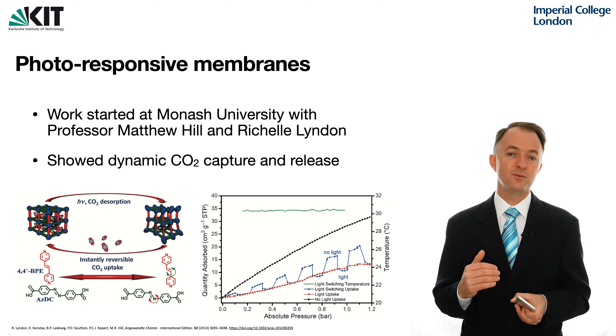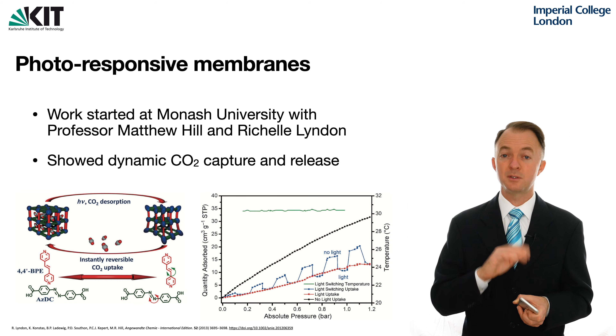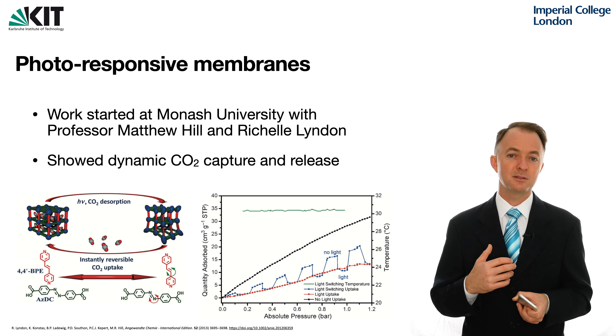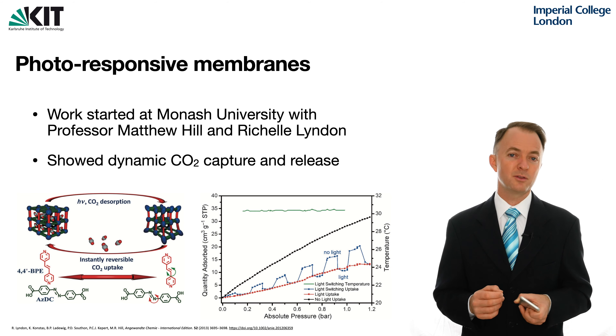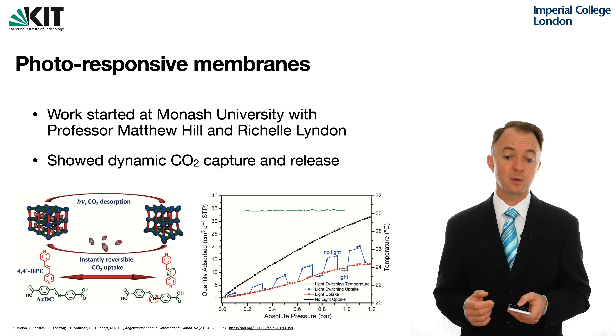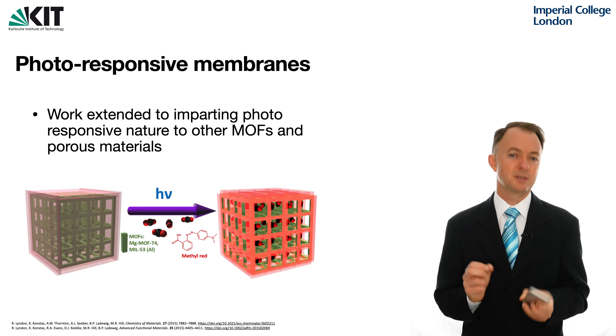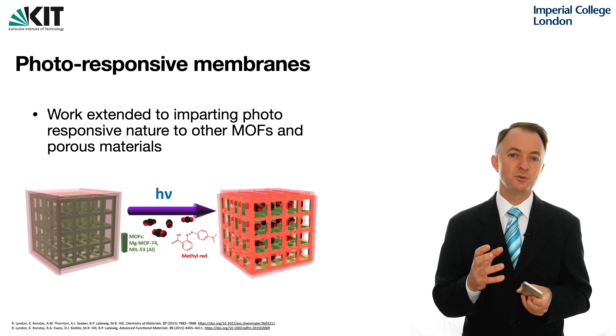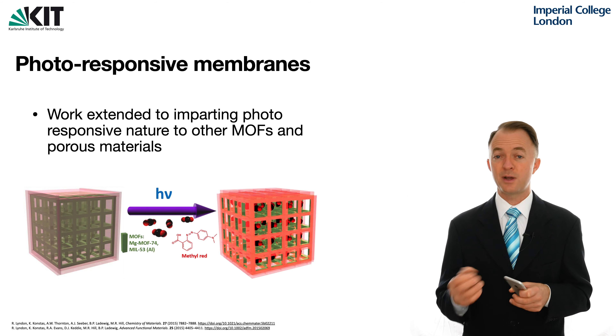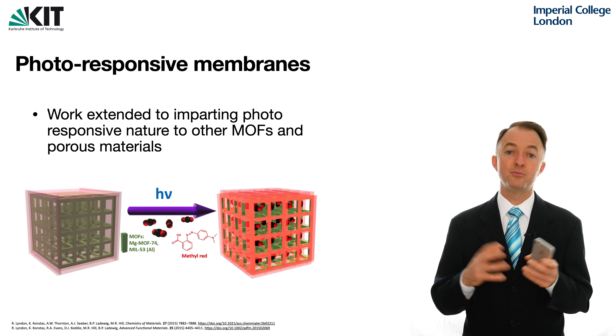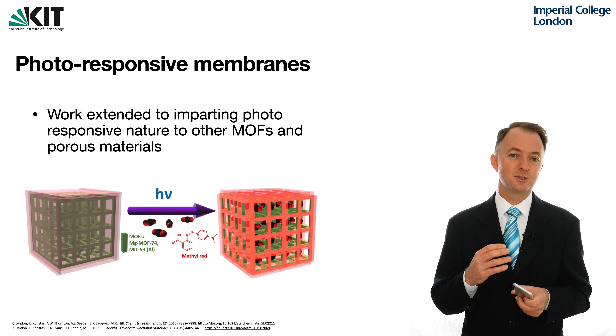It doesn't go fully to the point of the adsorption isotherm with no light, but it is substantially moving between the two. This was one of the first reports of dynamic photoresponsive CO2 sorption, and it led to us doing a lot more work in this area — many other groups around the world have also gone on to work here. We showed that it's possible not just using this type of MOF but also using other types of MOFs and other strategies: putting in guest molecules or coating the outside of MOF particles with different agents allows you to produce either a slow or fast photoresponse, broadening the field to show that different approaches can achieve a photoresponsive CO2 sorbent.